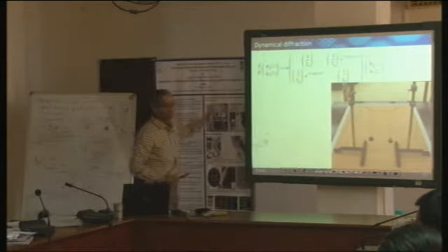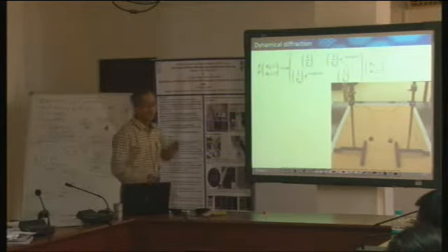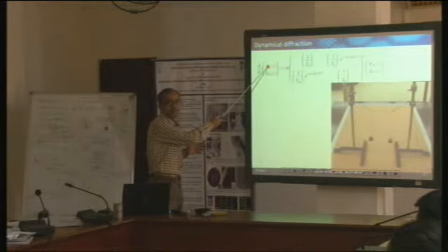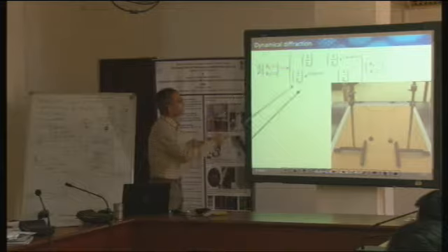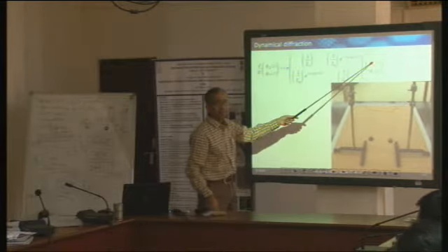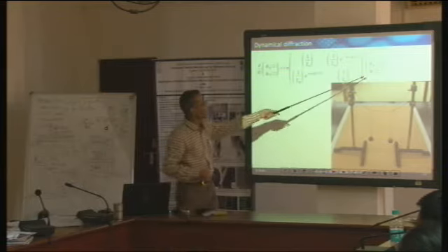In a way, this is written in a matrix form, isn't it? What this shows is that the rate of change of diffracted beam intensity depends not only on the diffracted beam intensity at that point, but also on what the zeroth beam intensity was at that point.